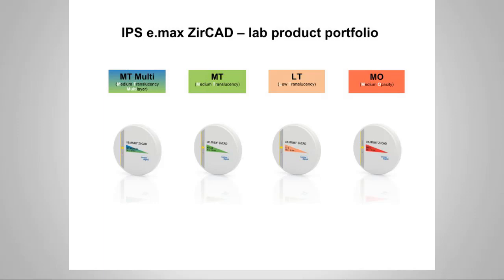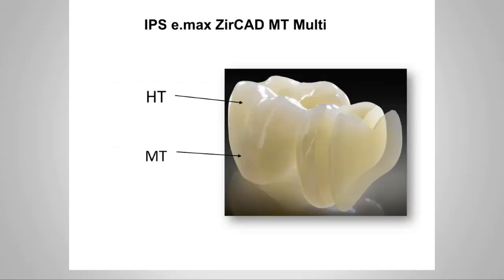Then beside that, you'll see the MT, the medium translucency puck, and then the two to the right are the LT, the low translucency, and then the medium opacity. The two to the left, the MTs, are going to be a 4 molar percent yttrium stabilized zirconia, and then the LT and the MO are going to be a 3 molar percent yttrium stabilized. So I'll show you sort of where these are best used.